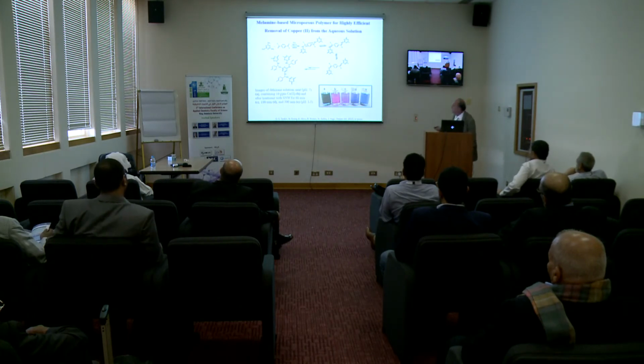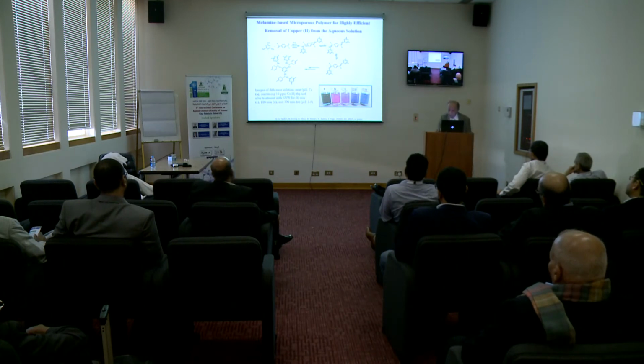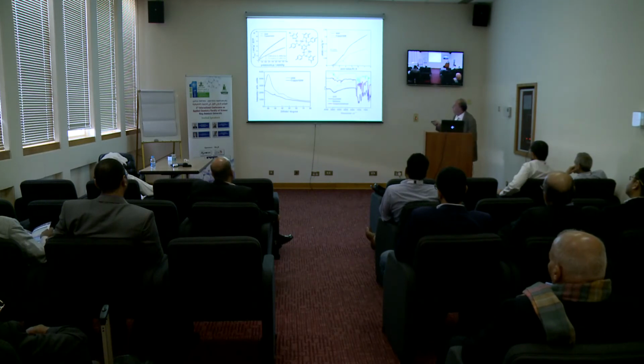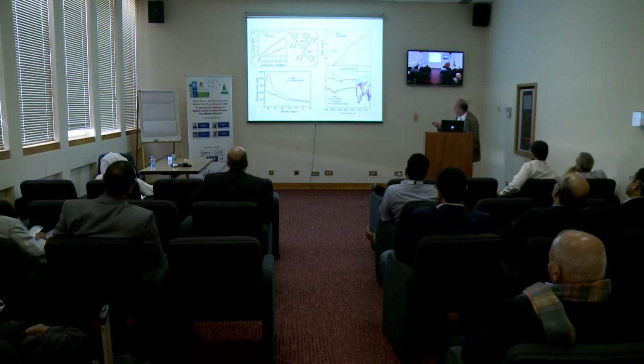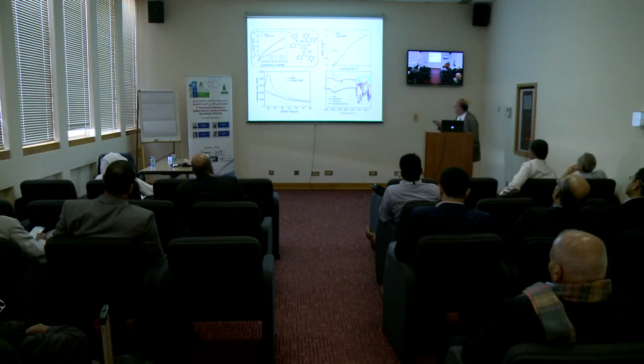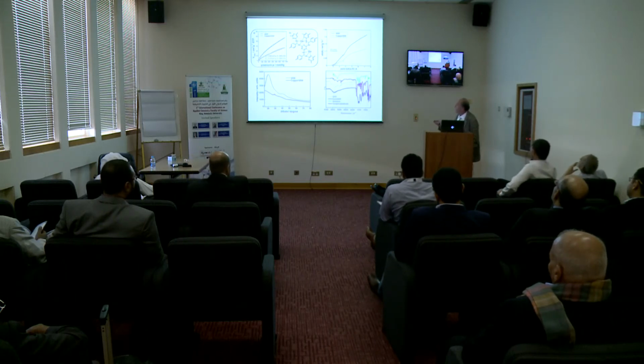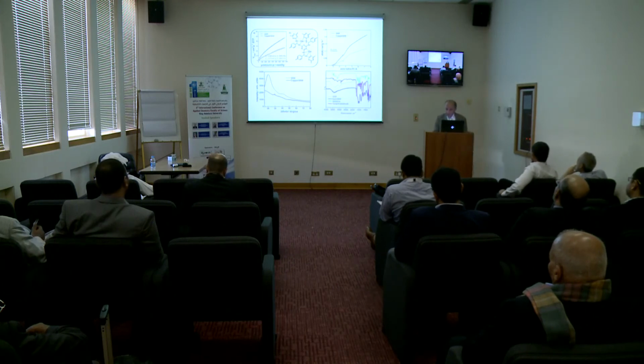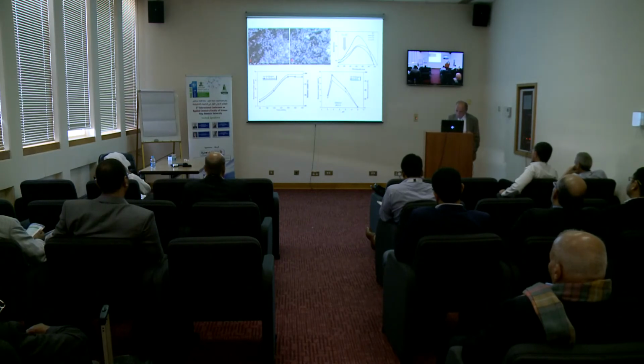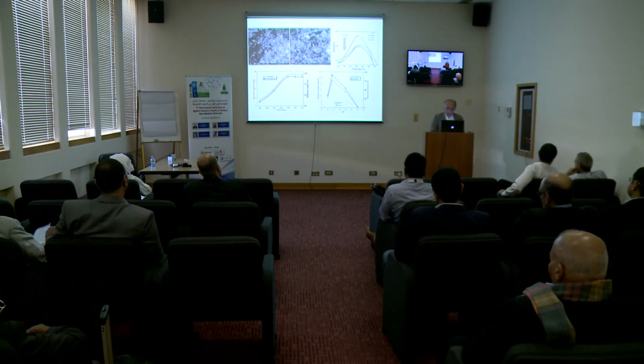And we have also melamine-based porous systems. You can see here they are networked, and this is the original solution. After treatment, you go back to the original by reuse. The copper interaction, again with the same materials, and we were able to show that they really interact with the porous material we have, and the infrared and other methods clearly provided this. And again, UV absorption, after 5 hours, the copper concentration is reduced. We defined the optimum pH, and almost all the copper is removed from the solution.